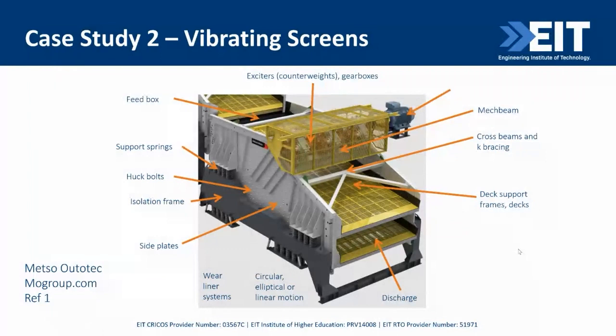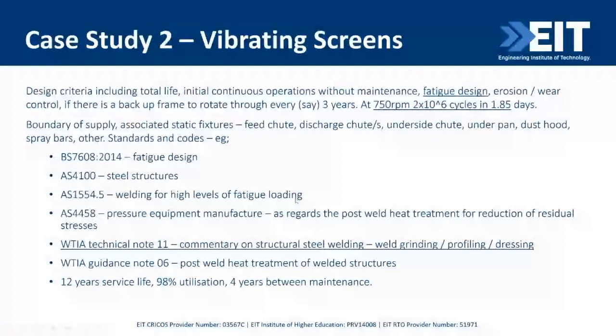So screens are similar to mills, a classic fatigue nightmare, but worse. They're a reciprocating machine, obviously, on the isolation frame with the spring supports, the body reciprocating back at plus or minus 5G as driven by the eccentric exciters, 600 to 900 RPM, and a very difficult design problem to say the least. So your criteria is less than 2 days, you're up to 2 million cycles at 750. And obviously you've got to do your fatigue design better. You may even use less than 2.3% failure criteria on your fatigue curve.